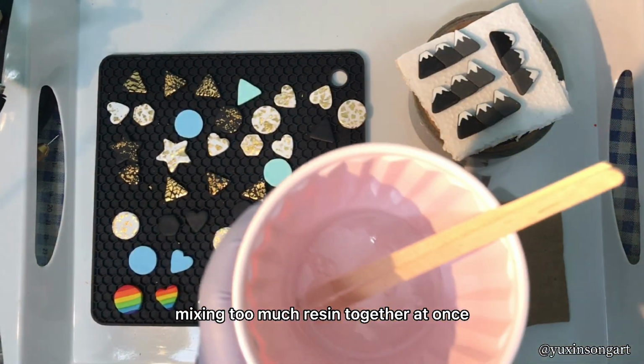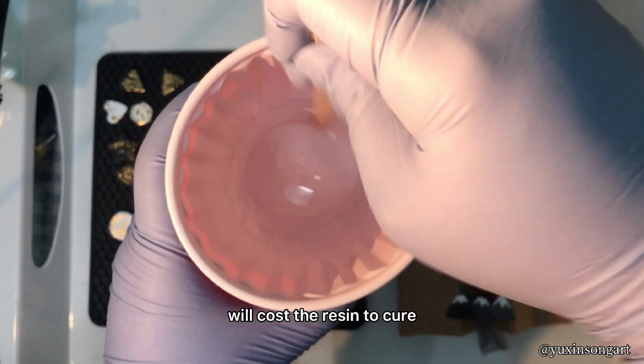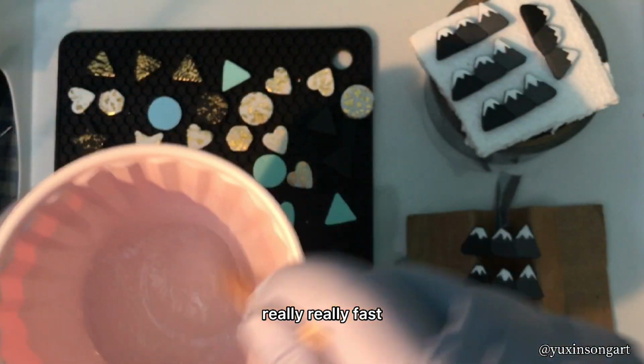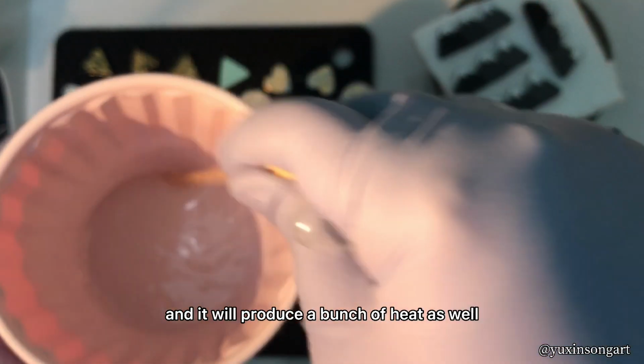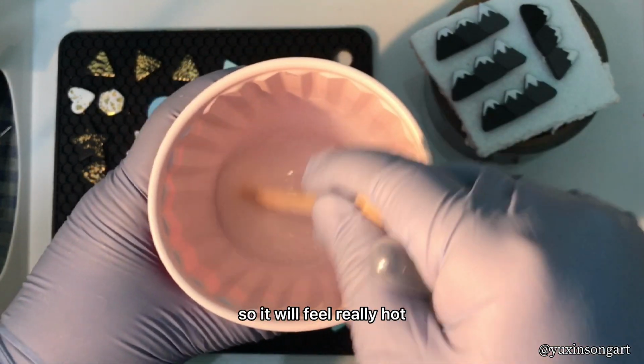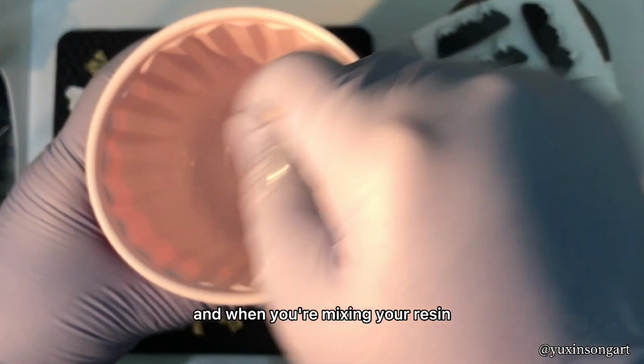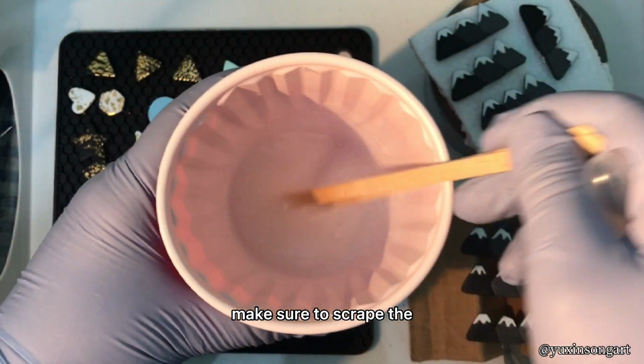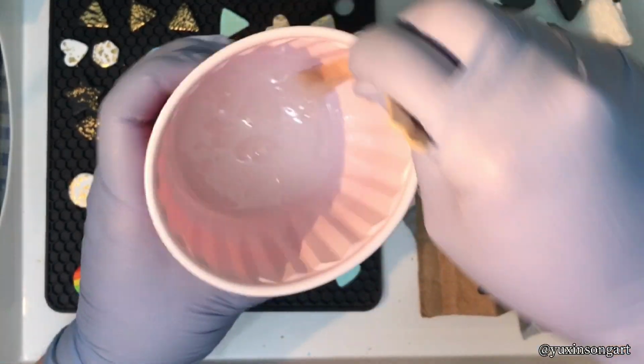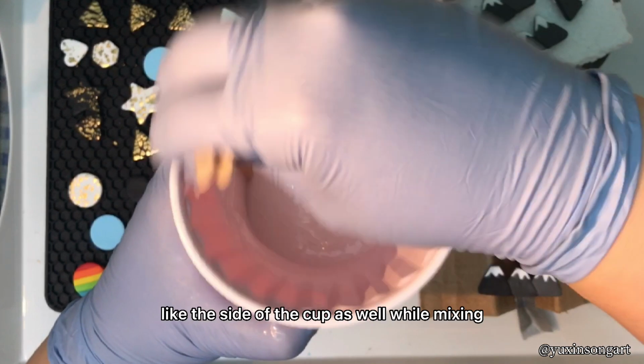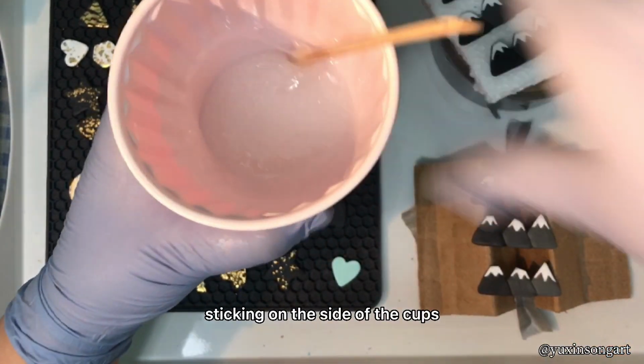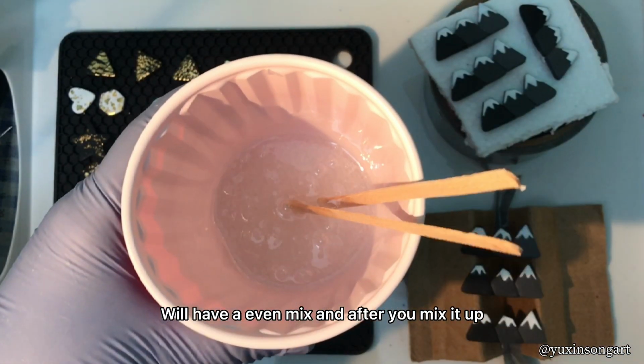Mixing too much resin together at once will cause the resin to cure really fast, and it will produce a bunch of heat as well, so it will feel really hot. And when you're mixing your resin, make sure to scrape the side of the cup as well while mixing, so that even the resin that is sticking on the side of the cup will have an even mix.